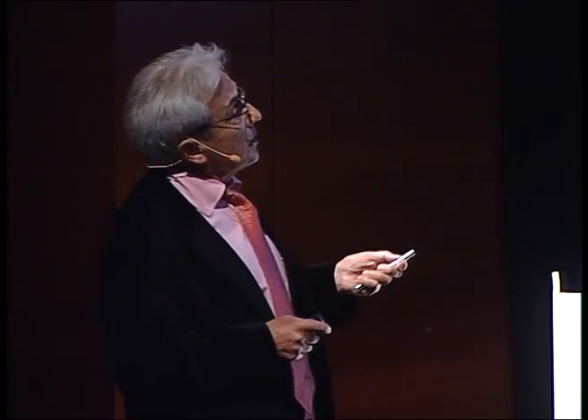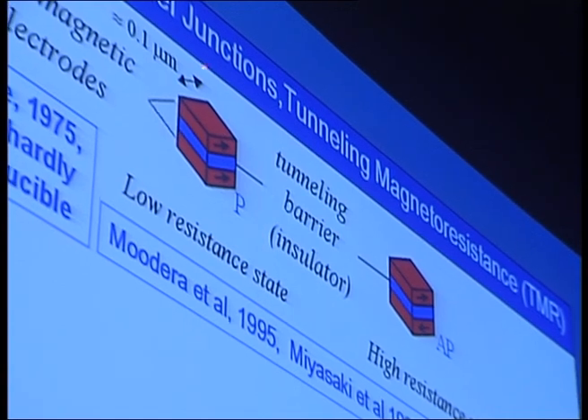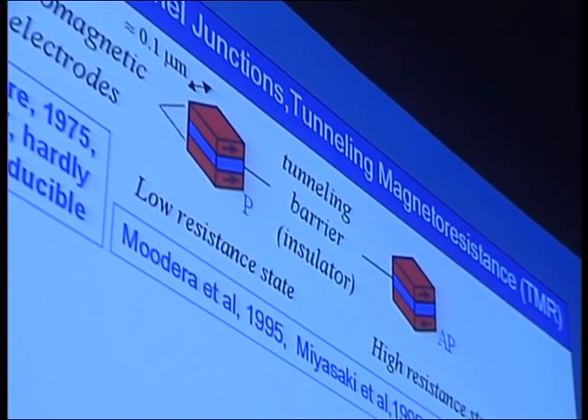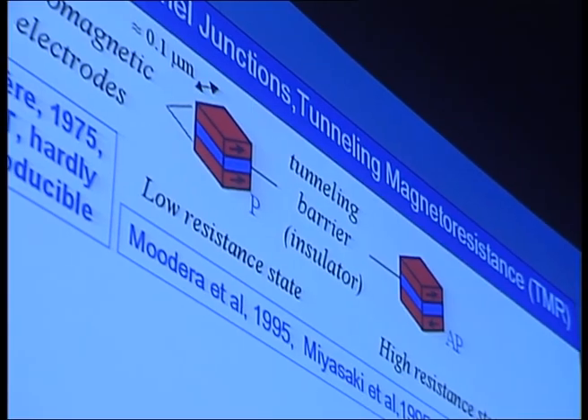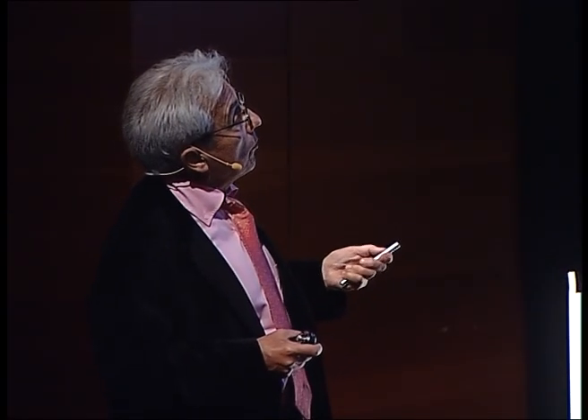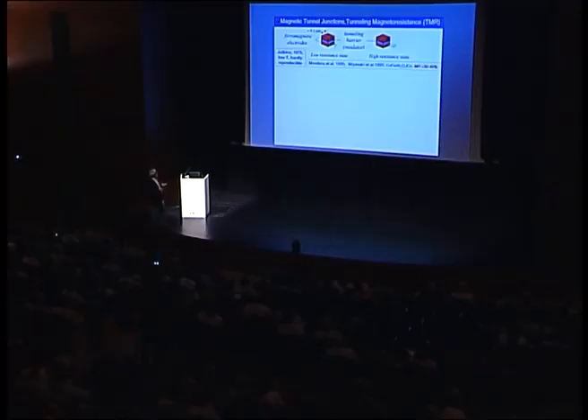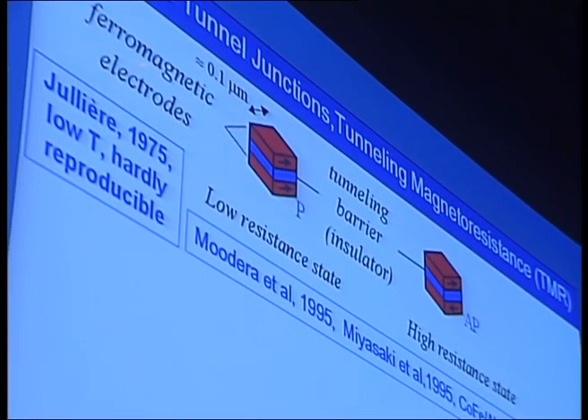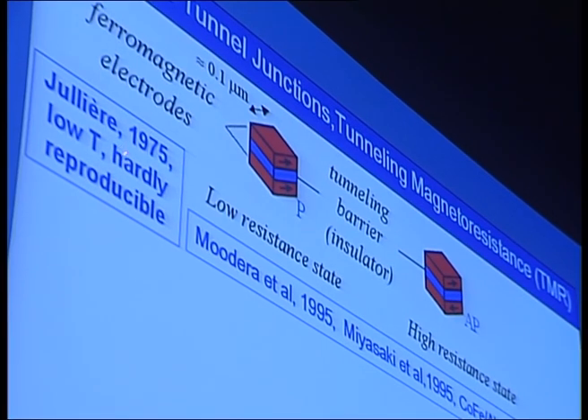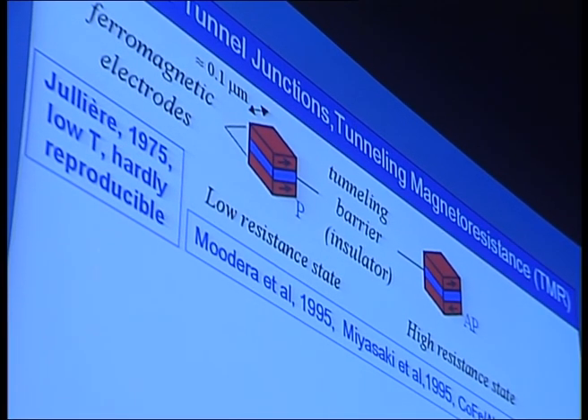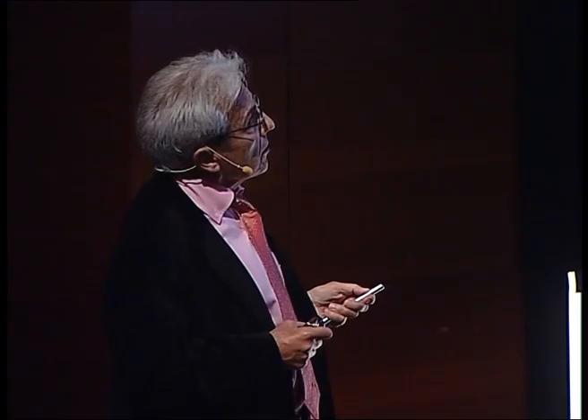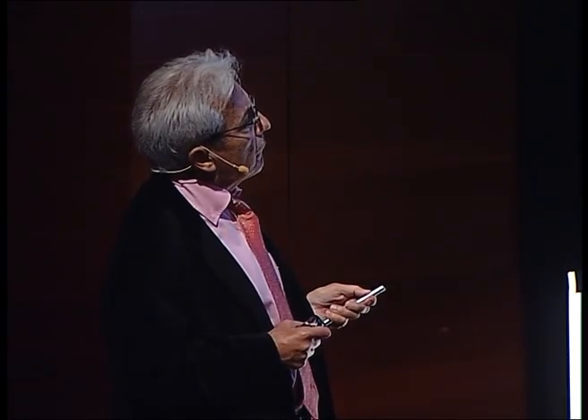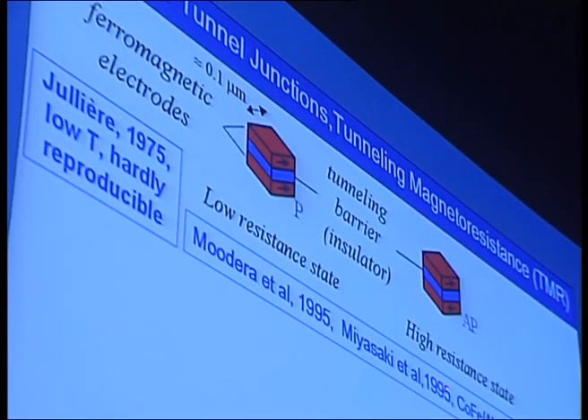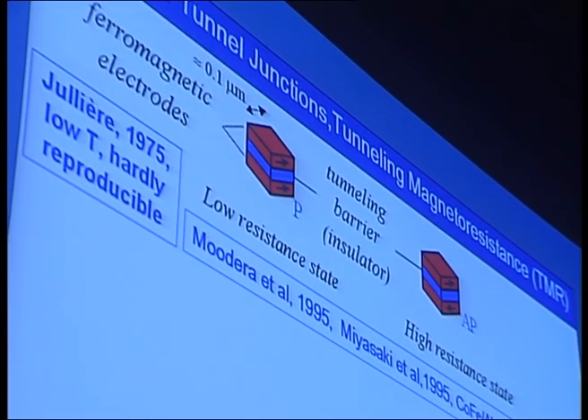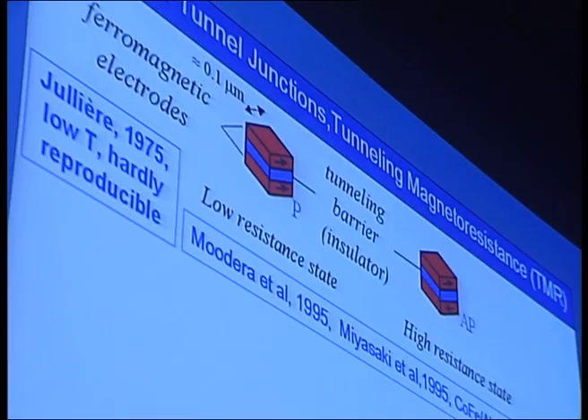The advantage is that with this vertical geometry of the current, it's possible to reduce the lateral size by e-beam lithography, for example, a new technique, and to have very small cells, very small devices. This effect, tunnel magnetoresistance, was observed but not very reproducibly in 1975 by Jullière. But these junctions are very difficult to fabricate. Now Moodera and Miyazaki in 1995 succeeded in fabricating a tunnel junction with an aluminum oxide barrier and obtained very reproducible results.